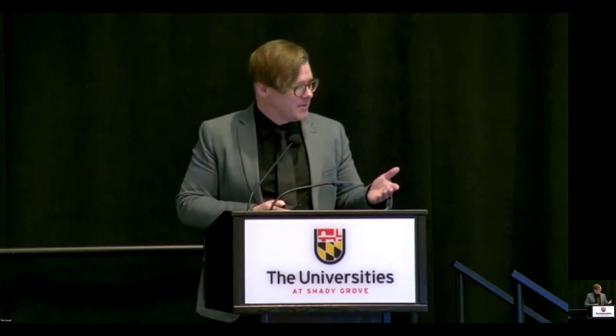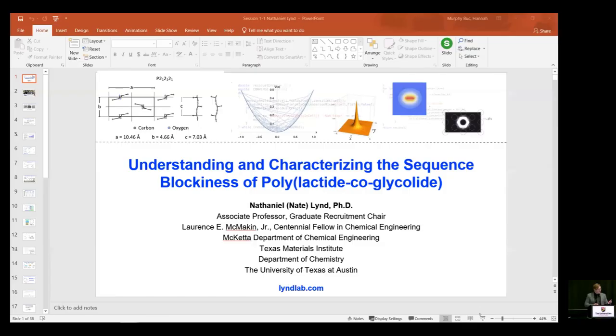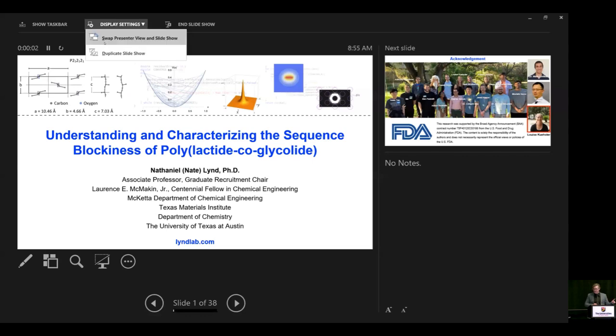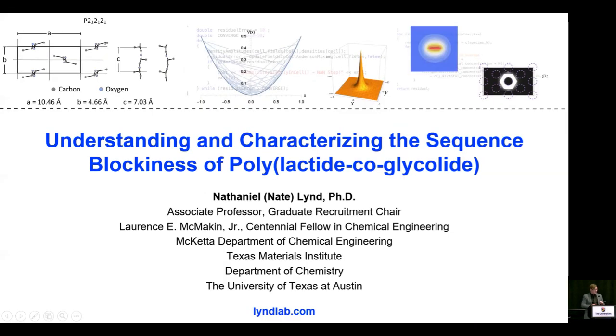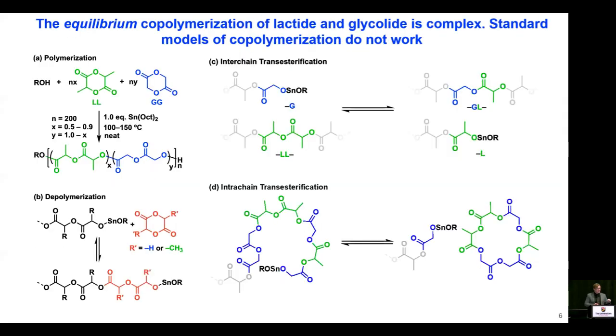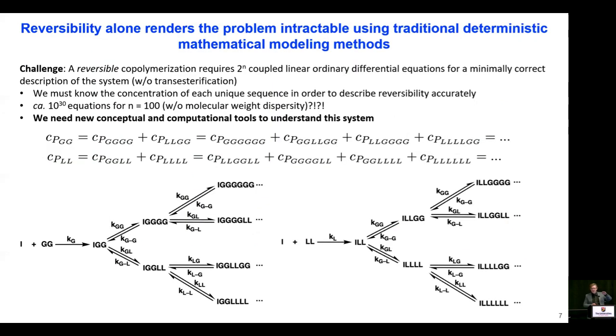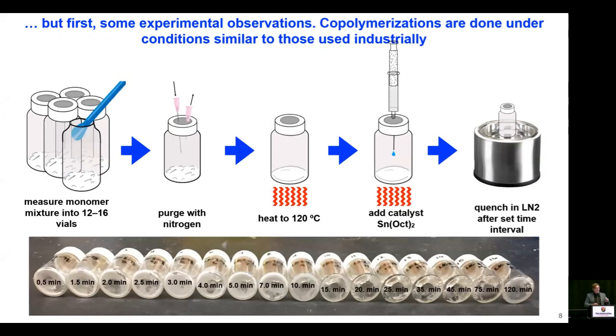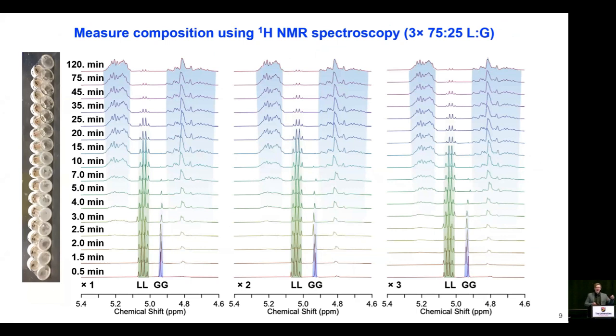Now, we had to make a lot of assumptions to do this, right? One was lactide only on the chain end. Glycolide is irreversible, and we didn't include the effects of transesterification because that is inherently non-deterministic. You can't treat it deterministically. And what we see is that there's some variation in the parameters that we determine as a function of the starting composition of glycolide. That tells us our simplified deterministic model is missing something. But we do have a starting estimate of all the parameters.